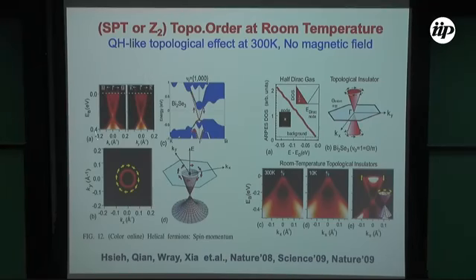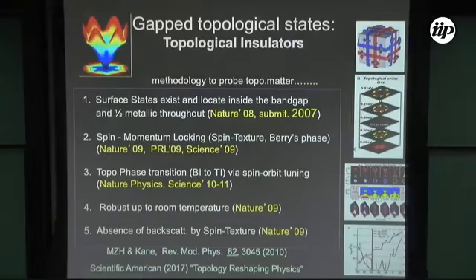This is one of the early demonstrations we had, that these helical Dirac fermions survive up to room temperature, and their backscattering can be tracked. This also allows us to count the density of states in the system, and then we can show that these are like a half Dirac gas. What is interesting is that now we can see topological effects at room temperature without a magnetic field, which makes the device and application community excited about these things, because you want to operate at room temperature without a field. So that's one of the reasons many people are working on it.